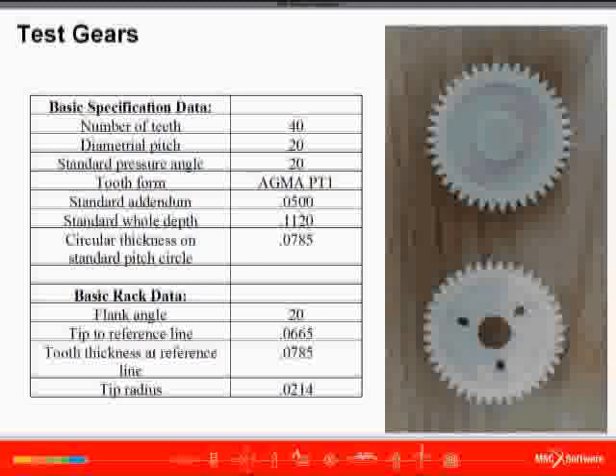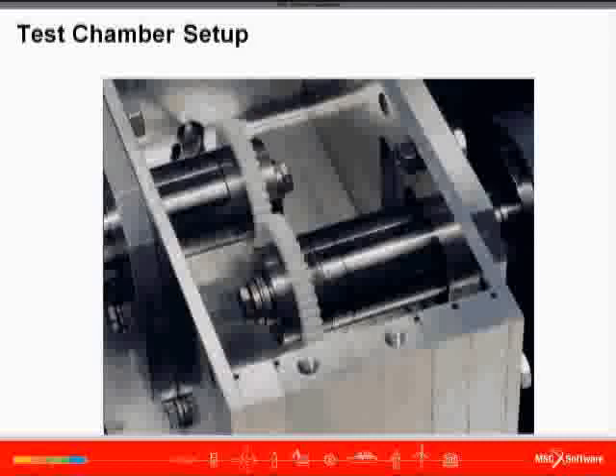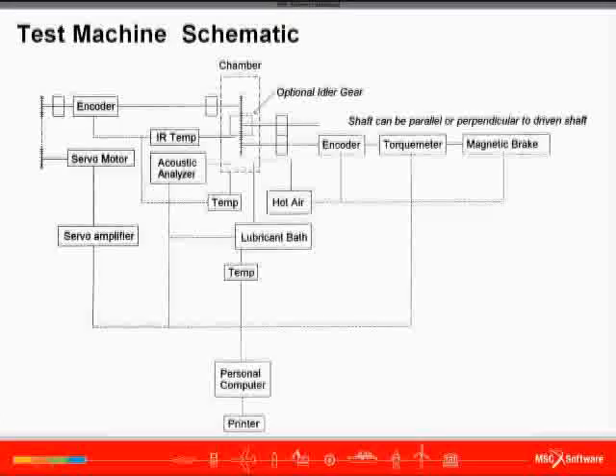A parallel axis testing machine developed by Ticona was used to load and record the load displacement response of the gears. The test gears were lubricated with oil prior to loading to eliminate any shear forces acting on the tooth flanks. A schematic of the test is shown here.